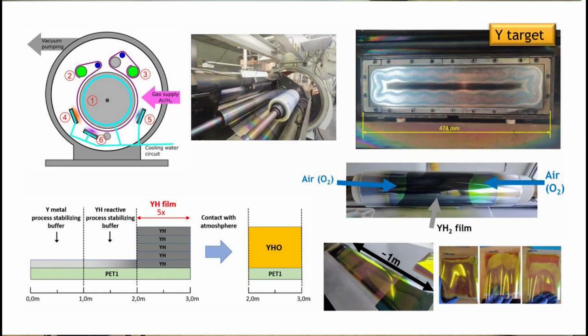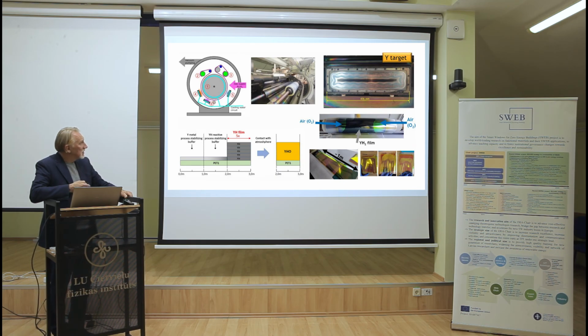photochromic. We have also developed, probably first in the world, the deposition roll-to-roll on a PET roll, together with the company Sidrabe, with which we are rolling this film near the magnetron that you see here. The magnetron is an yttrium magnetron in the atmosphere of argon and hydrogen, and we obtain many layers. We go up and down, and we obtain such a film. But after opening, we see that this film starts to be completely transparent and photochromic.